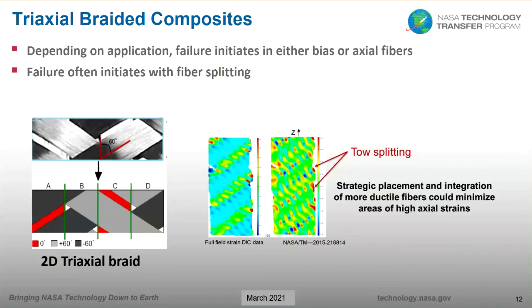And depending on the application, studies have shown that failure can occur in either the bias yarns, those yarns being highlighted in the gray area, or the failure can initiate in the axial yarns, and those are the yarns highlighted in red in the A and C columns in this image. In almost all of those cases, failure initiated by fiber splitting.